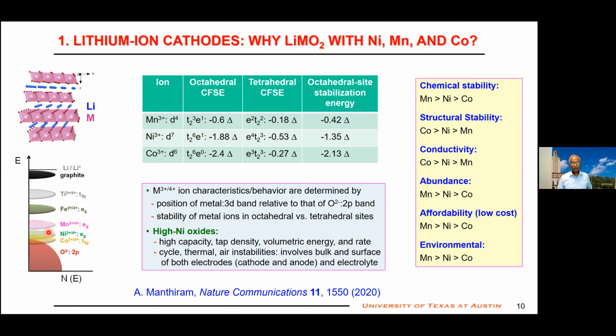That means we are oxidizing oxide ion into superoxide, peroxide, and then finally oxygen will be evolved. So that's why even though with lithium cobalt oxide, it will say on your laptop 100% charge, it is not 100% charge, it is only 50% charge. If we charge more than 50%, we will have safety problems as well as cycle life problems. Manganese, on the other hand, is well above the top of the oxygen 2p, so we can go all the way up to manganese 4+. There is all kinds of manganese 4+ oxides, alpha, beta, gamma, delta. So many Greek symbols are running out. So manganese is chemically stable. Cobalt is chemically not that stable. That's what you see here.